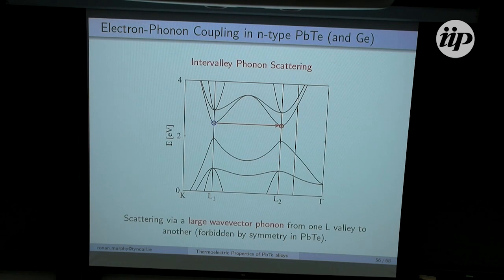So to model electron-phonon interaction, we subdivide the different processes into whether they occur by a large wave vector phonon or a short wave vector phonon. I'll first talk a bit about the intervalley phonon scattering case, which is via a large wave vector phonon. This is the electronic band structure of lead telluride. It has 4 equivalent L valleys, and you can imagine an electron scattering from one L valley to another L valley via an X-point phonon. As luck would have it, in the case of lead telluride, this particular scattering mechanism is forbidden by symmetry. But if we take the case of germanium, it's not. So we do have to take that into account there.